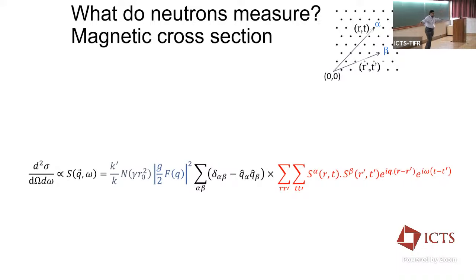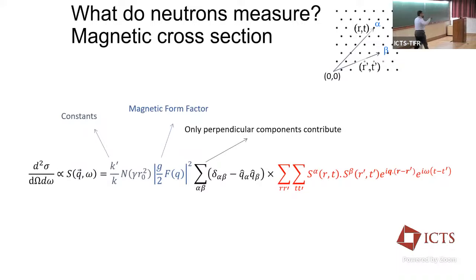We get terabytes of data from one single neutron scattering experiment, and then we take that data and slice it up into several Q vectors, looking at the high Q vectors for the phonons and the low Q vectors for the magnetic information. If I break up the overall scattering cross-section, it has some constants, then the magnetic form factor, which is important because that's how we know what is magnetic and what is not. Anything which falls off like the magnetic form factor must be magnetic. Then we have selection rules which tell you which direction the spins are pointing and which direction the spins are fluctuating.